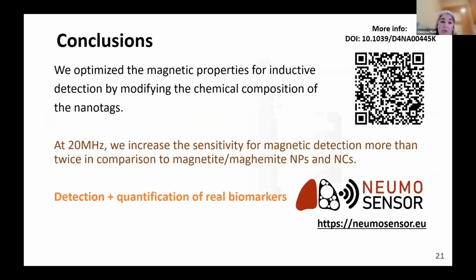So to conclude, we optimized magnetic properties for inductive detection by modifying the chemical composition of the nanotags. At 20 megahertz, which was the frequency we used for our measurement, we increased the sensitivity for magnetic detection more than twice in comparison to our best previous results with magnetite nanocluster. And now we are working with detection of real biomarkers for the detection of pneumonia infections.